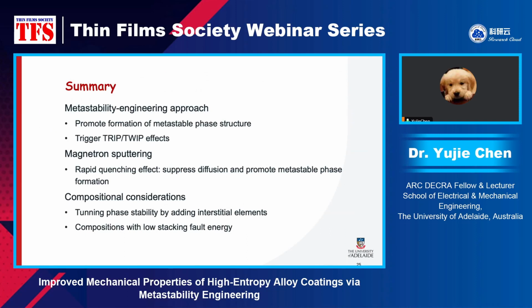Okay, to sum up, in this talk we mainly focus on the metastability engineering approach. What we do is promote the formation of metastable phase structures, such as the FCC and HCP dual phase structure. And we want to trigger the phase transformation and the deformation twinning, because this will give us larger plasticity that will make the material tougher. To achieve this, we use magnetron sputtering because the rapid quenching effect can suppress the diffusion and promote the metastable phase formation. With metastability engineering, we need to form the metastable phase first, right?